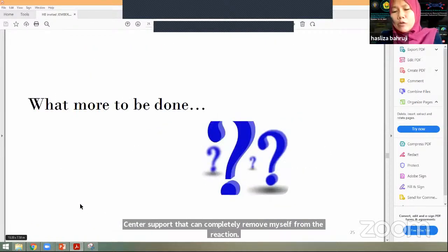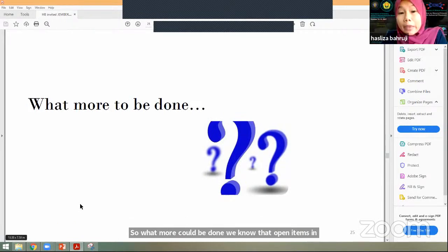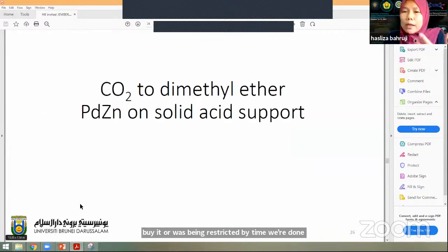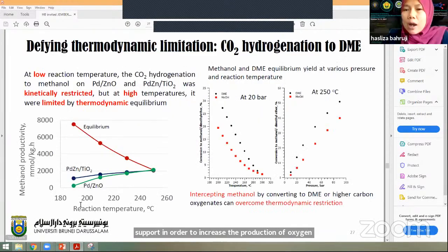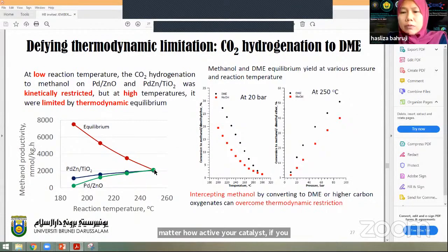So what more is to be done? We know that our palladium zinc catalyst is very active to generate methanol from CO2, but it is always restricted by thermodynamics. So can we put palladium zinc alloy on a solid acid support in order to increase the production of oxygenated products at high temperature? We try to defy the thermodynamic limitation by carrying out an experiment to conduct CO2 hydrogenation further to dimethyl ether. This is the equilibrium, the theoretical product that we can obtain when we use the palladium zinc or palladium zinc oxide catalyst, where we can see that up to 250 degrees Celsius, no matter how active your catalyst is, you cannot surpass the equilibrium restriction.